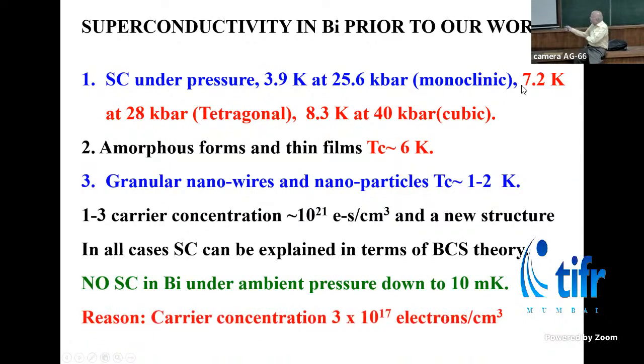So before we came into this picture, there was superconductivity in bismuth under pressure. Then there is amorphous bismuth, which shows superconductivity at a fairly high temperature, 6K, and nanowires. See, none of these is bismuth in its pristine form. Under pressure, the structure changes. You are not dealing with pure bismuth at ambient pressure or temperature. So most of these cases we can explain by BCS or an extension of the BCS theory.